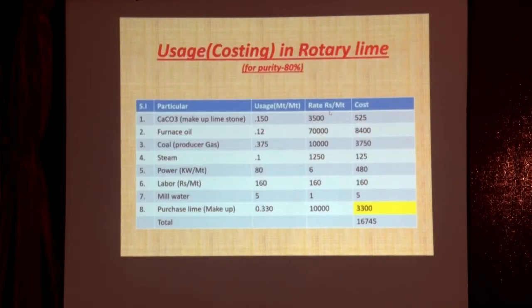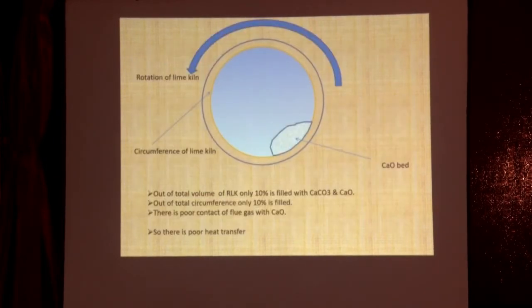This is a rotary lime kiln, how it works. Usually it rotates in the anti-clockwise direction, but it may be clockwise also. If you see the bed, I think not more than 10% of the volume of this whole rotary lime kiln is occupied. The remaining whole kiln is empty, this blue portion. So only 10% is filled with calcium carbonate and CaO. Out of the total circumference, only 10% is filled.